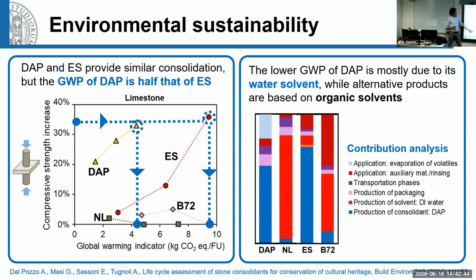So we obtained some graphs like this one, which I think are quite interesting, where we plotted the increasing compressive strength. So we start from a certain megapascal of compressive strength and then we increase it as a function of the global warming indicator, so amount of CO2. So the idea is, for instance, if your stone is very deteriorated, so you need a 35% increase in mechanical properties, so a strong action. Okay, DAP is able to provide this mechanical improvement with a certain CO2 emission. This consolidant here wasn't very effective, same for this one. The only other consolidant that was able to provide such high consolidating effectiveness was ethyl silicate. However, in this case, the amount of CO2 that is produced is basically twice as much compared to the phosphate treatment, the DAP treatment. Why?